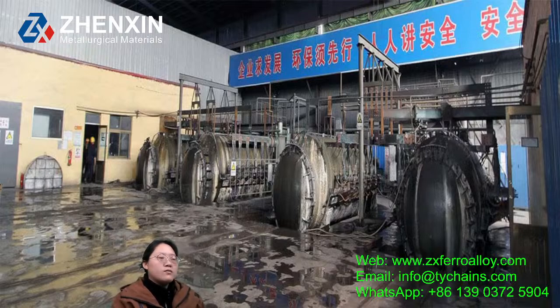Ferronickel 20 has a nickel content between 18% and 22%, the mainstream grade for 300 series stainless steel production. And Ferronickel 30 has a nickel content between 28% and 32%. It's also a premium grade for specialty steel and precision alloys.